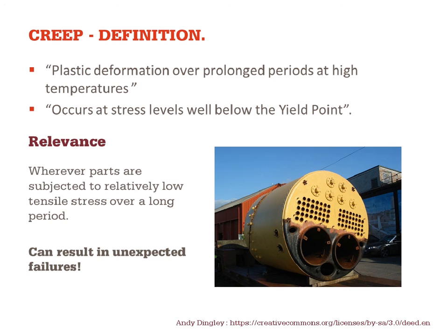But other mechanisms come into play, and creep has to be measured to understand the circumstances under which long-term deformation happens. And it can result in unexpected failures where, if you rely solely on the tensile data, you would say this heat exchanger boiler is not going to fail. Well, actually, it's subjected to long-term stresses at reasonably high temperatures, and in that case it did fail. So we have to be conscious of that.